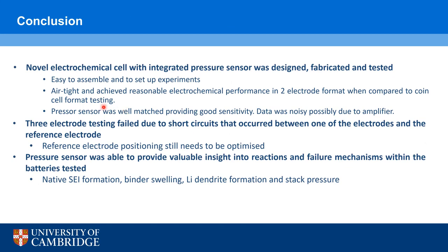In conclusion, we were able to design and test a novel electrochemical cell, which was easy to assemble within the glove box, and provided an airtight environment to perform electrochemical tests on 2 and 3 electrode cells. Unfortunately, in the 3 electrode cells, we still need to work on optimizing the positioning of the reference electrode, but in the 2 electrode format, we were able to get some nice data. The pressure sensor was well matched in terms of sensitivity, and we were able to get good insight into the battery in terms of native SEI formation, binder swelling, and dendrite formation.